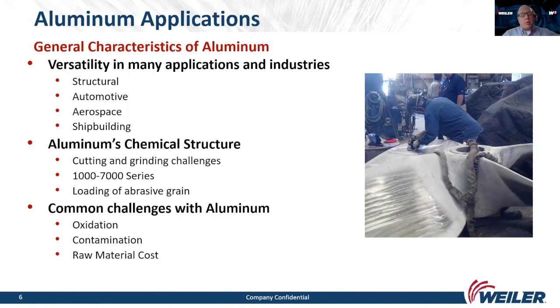So after I had that discussion with that distributor, I sent the Tiger angled ceramic flat disc to the end user direct. And that's an excellent flat disc for grinding on aluminum. The disc was $2 higher than what they were paying for with the previous disc, but they went with it. The reason they did is because they had considerably less loading issues. It was rated contaminant free, and I'll clarify more what that means a little later in my talk. It also allowed them to reach and grind welding fillets in angled locations. So all around, this saved them money and time since they weren't changing discs very frequently.